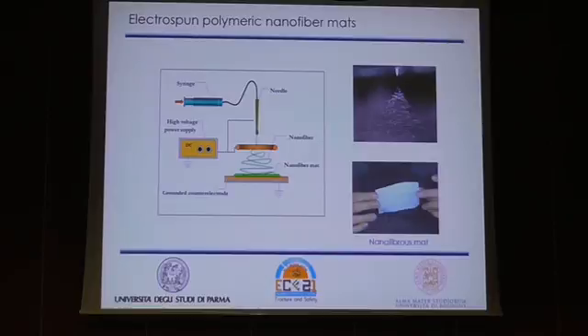Firstly, let me spend a few words to describe the electrospinning technique used to produce the nanofiber mats. The polymeric solution with some solvent was injected into a capillary tube and then in a needle, kept in tension by a high voltage power supply. When the electric field reached a threshold, the repulsive electric forces became higher than the surface tensions, and therefore the polymeric solution was ejected from the needle and was whipped in the path between the needle and a ground collecting plate, in which the electric charged jet was divided by the electric field into a multitude of nanometric fibers stacking on each other to form a mat whose thickness could vary from some micrometers to some nanometers.